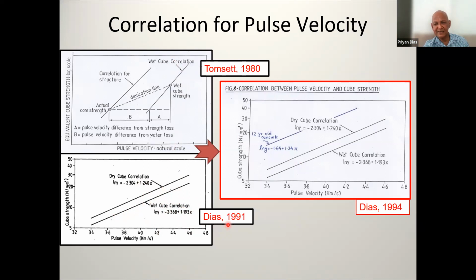So this is published in the Engineer Journal 1991. So you can see there's a difference between dry cubes and wet cubes. Now, at that time, this was interpreted by this fellow called Tomsett, who says that, okay, this is what is called a wet cube correlation, dry cube correlation, right? Now, actually, he was also talking about the difference between a construction site here, which is dry. This was the structure, actually. Here we have the structure, and the cubes that you take from it, cubes before it went into the structure, right? So these cubes are, of course, cured under wet conditions, right? And then just before you crush it, you can do a pulse velocity test, right?